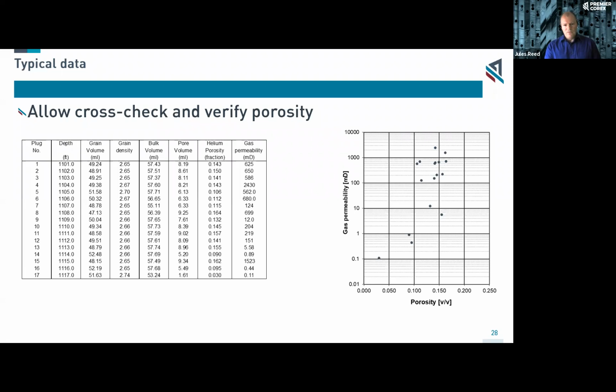The grain volume and bulk volume help us to understand the porosity data. And we can make our own calculations and check that we agree with the porosity, and we find that these are reasonable. So the data on the right stands as it is.